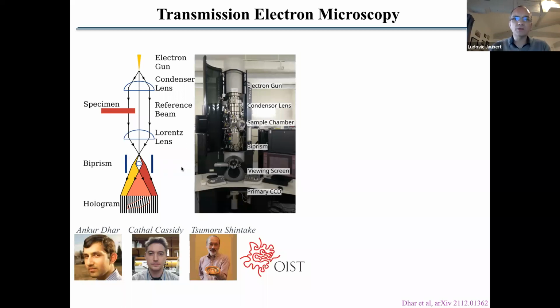So first, I'm going to give you a very brief presentation of electron holography for theorists. Essentially, you get an electron beam coming from the top here, which is coherent. Then you use a lens to diverge this beam into two different beams. One of these two beams goes through the sample, and so by going through the sample, the electron beam gets a phase. I will go back to that one later. And then you recombine these beams together, and you use the biprism to diffract it.